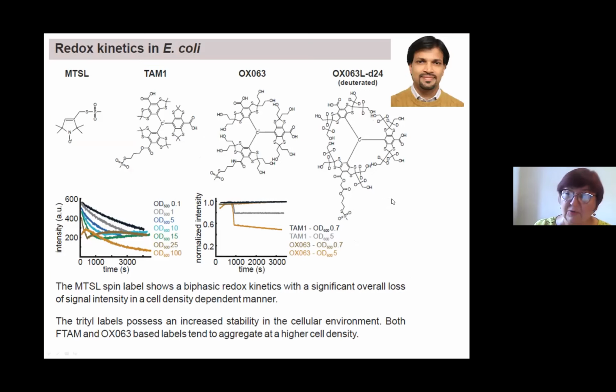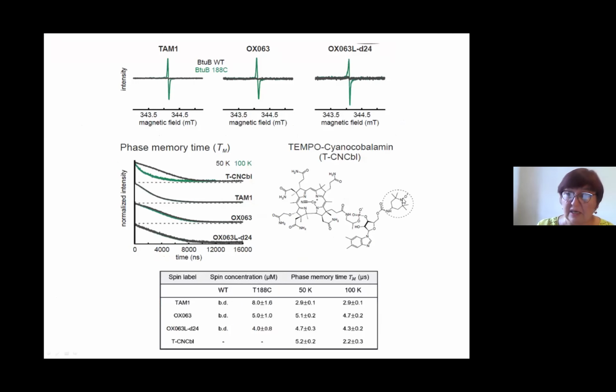Last work, not last work, but during this year, a work which was recently published together with Tom Benesh, who now has his own group, we performed experiments with different spin labels. First of all, we observed that they are very, very stable in comparison with nitroxide. In some cases, biologists need several procedures, and the spin label should be very stable to perform some experiments. This is one point. The second point is that he observed again for OX063 quite long electron spin relaxation in comparison with others.